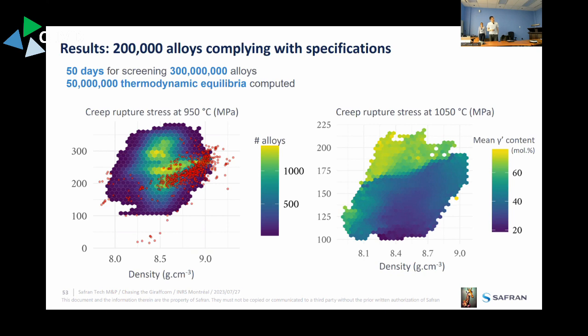And those are represented here. On the left figure, the y-axis is the creep resistance at 950 degrees Celsius, so the higher, the better. Density is on the x-axis, sorry, and lower is obviously better, because lightweight materials tend to resist more because they have less stress applied to them. The hexagons there are the 200,000 alloys, with hexagonal binning, and the number of alloys is the color. And what you see in red is the existing alloys from the database. I always found this graph nice, because the position of them compared to the position of what we screened showed an increase in specific creep resistance. So it kind of shows that, numerically speaking, the margin of improvement was indeed exploited.